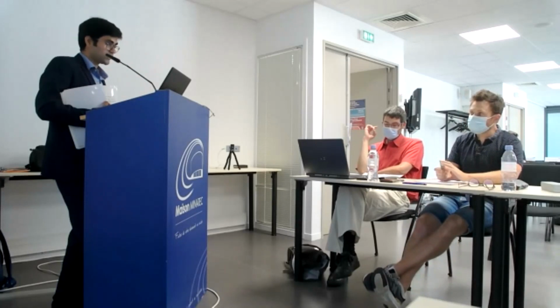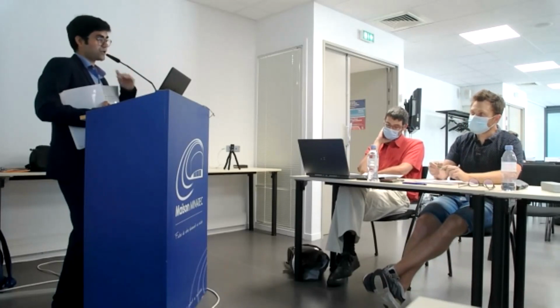The second aspect could be thinking out of the box in terms of processing, how we can control the cooling rates, for example, probably using twin lasers, we can have larger dendritic arms, larger dendritic arm spacing, which is able to accommodate the liquid into the dendrites so that you have less cracking. So I think controlling cooling rate in L-PBF can also be thought of as a perspective. So I would prioritize it second in my list. The third one can be